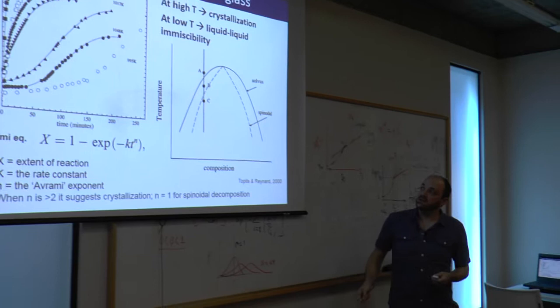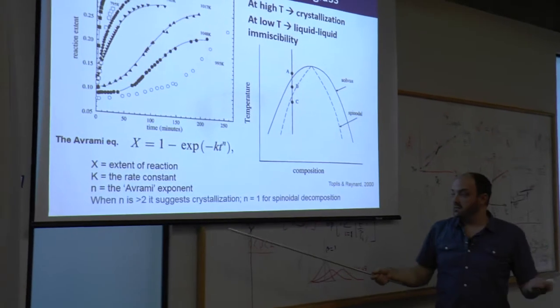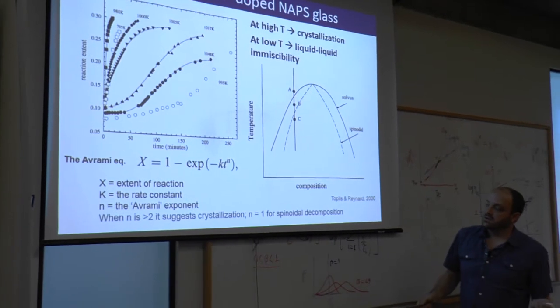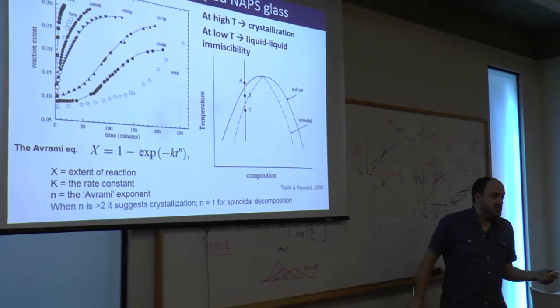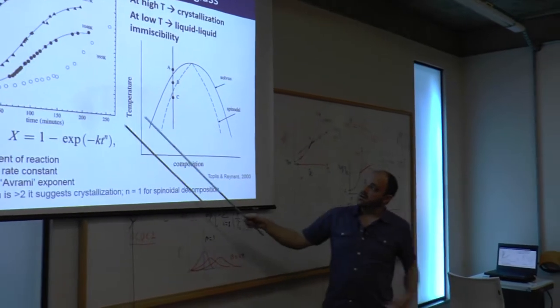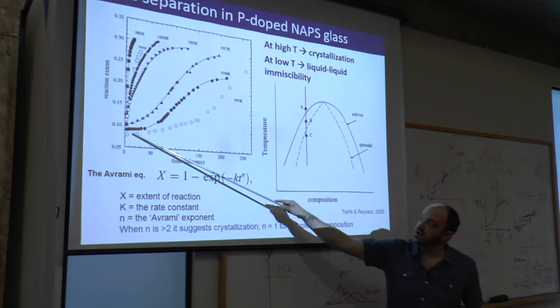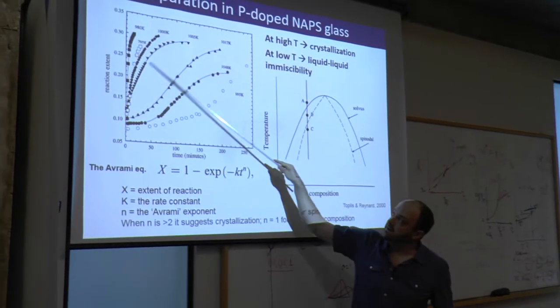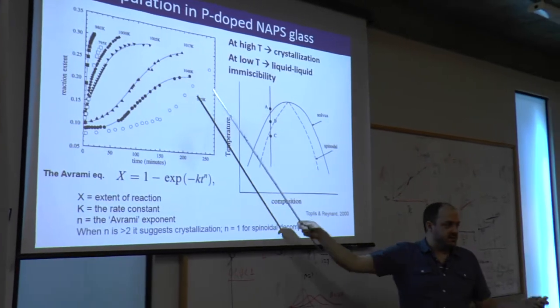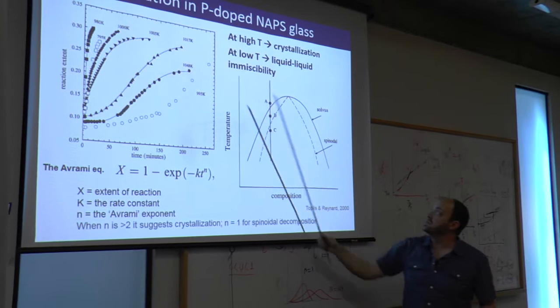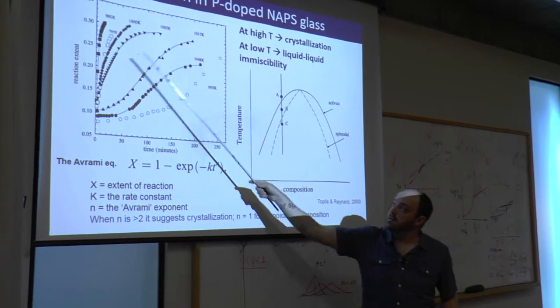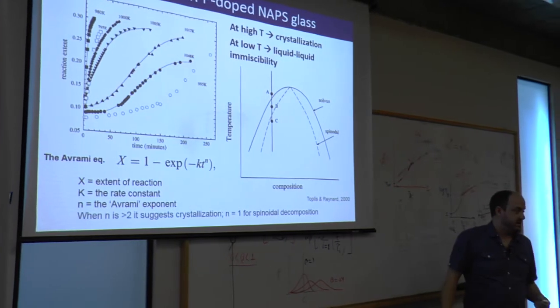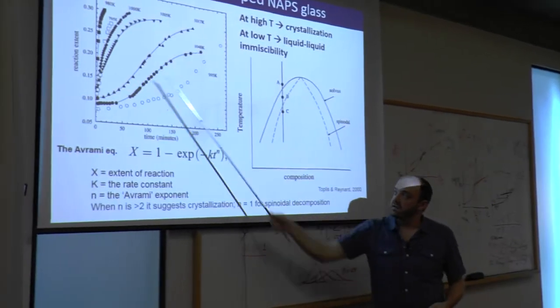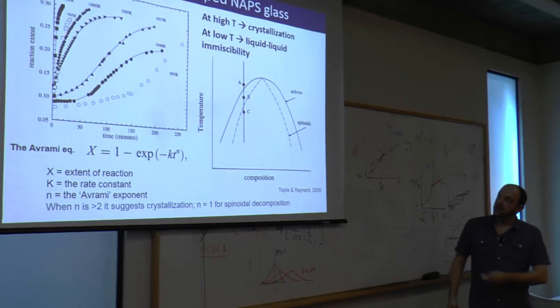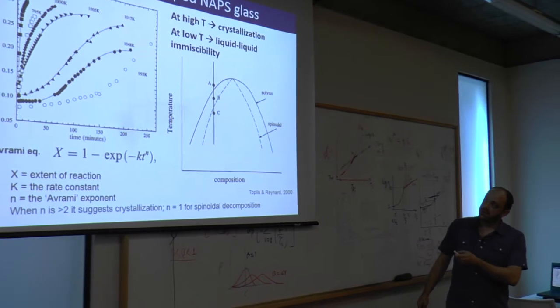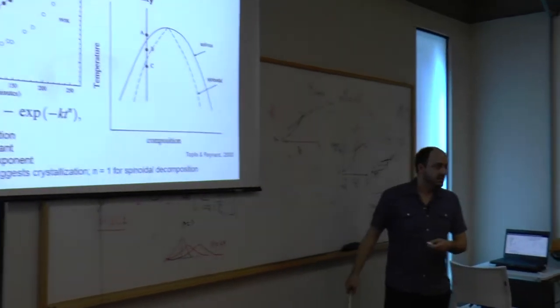time. And what they said is that when they fitted this Avrami exponent, when it's close to 2, it suggests crystallization, and when it's around 1, it's related to spinodal decomposition. So their interpretation was that these curves at high temperature, where the reaction is quite slow, much slower than at low temperature, which is the inverse of what you would think, are related to crystallization above the solvus. But when you go to low temperature, you're down in the spinodal field where these phases stay separate. And they can actually follow the kinetics of this with time using the Avrami equation. So they can very clearly characterize the differences between these two processes.